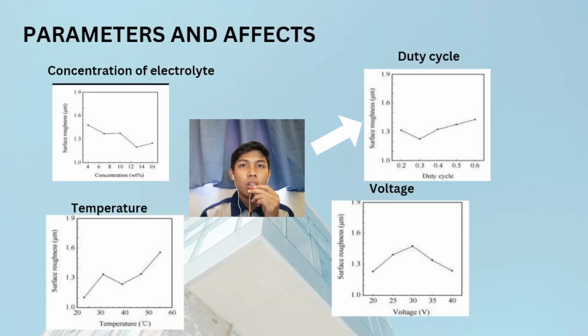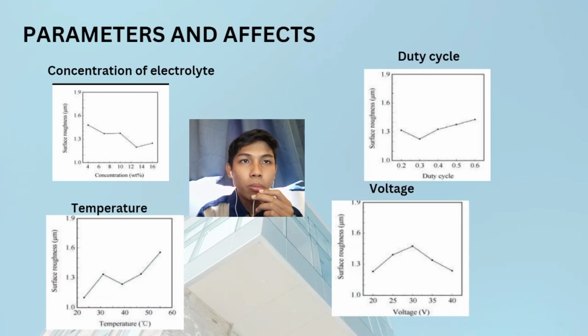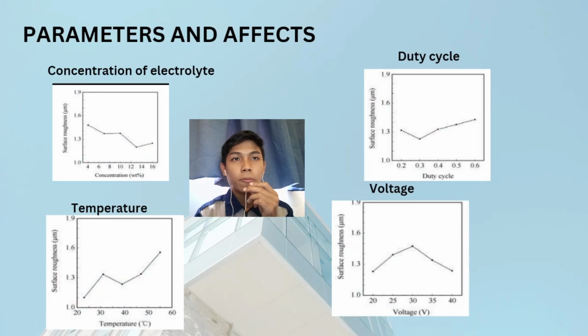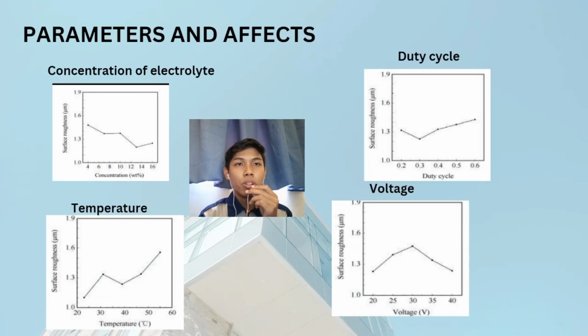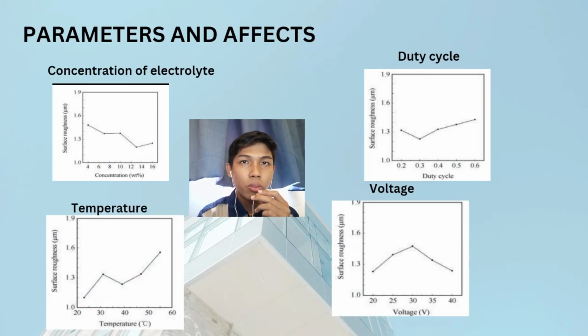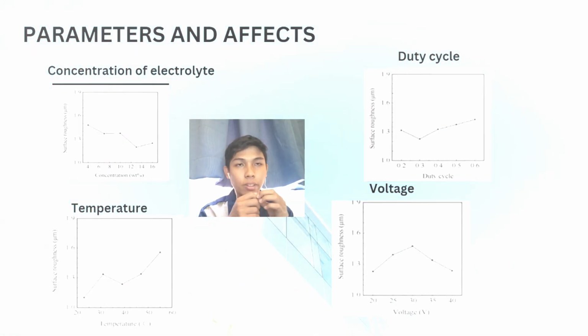The duty cycle. During the condition of a low duty cycle, the processing time is very low, and this can be enough time for the removal of the electrolytic product. And at a duty cycle of 0.3, by referring to the graph, we can see that the surface roughness is good.